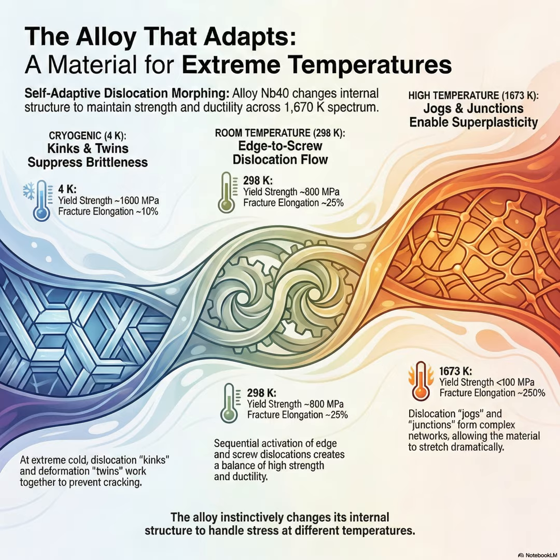And the secret sauce they found, the mechanism, is this concept of self-adaptive dislocation morphing. It's basically proof that you can design a material that changes its fundamental strategy for dealing with stress depending on the temperature. It's like the alloy has an internal toolkit, and it just knows whether to pull out a hammer or a wrench depending on if it's freezing or frying. That's a great analogy. So let's set the stage.